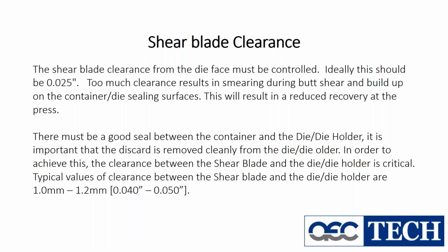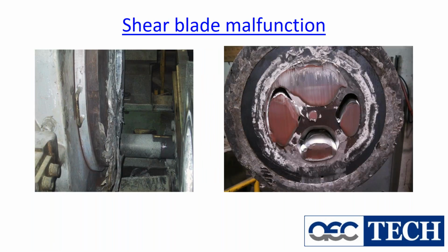This will contribute to a problem with recovery. There has to be a good seal between the container and the die holder. It's important that the discard again is removed cleanly. Typical values of clearance between the shear blade and the die are 1 millimeter to 1.2 millimeters or 40 to 50 thou. So again, work with your tooling people, work with your technical people, find something that you're going to work with, and then just monitor it.